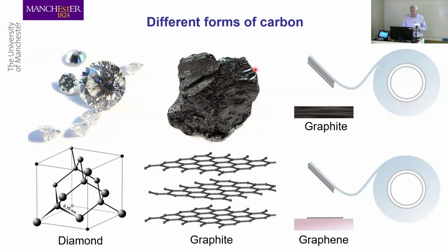And the very simple experiment that was done by my colleagues in Manchester 20 years ago was to take some graphite and to use some adhesive tape, peel off layers and then press a layer onto a substrate and pull it off, and you end up with a single layer of the graphite lattice. So this graphite can be split into individual single atomic layers. And this work really revolutionized an area, and the whole area just exploded enormously because this material has some really